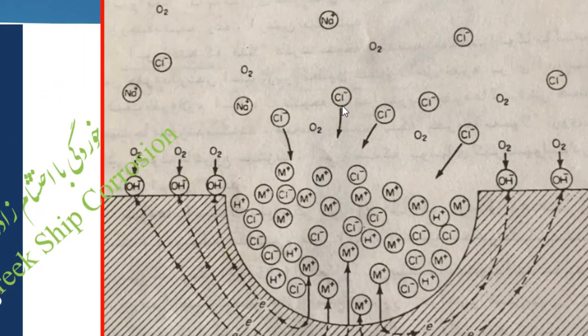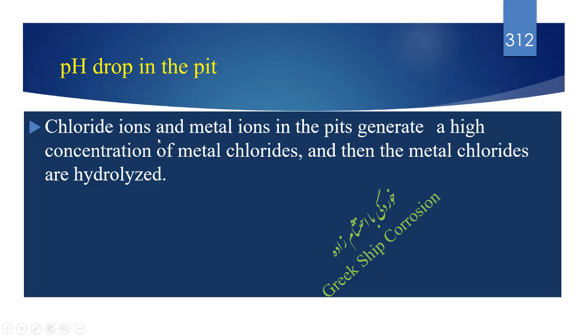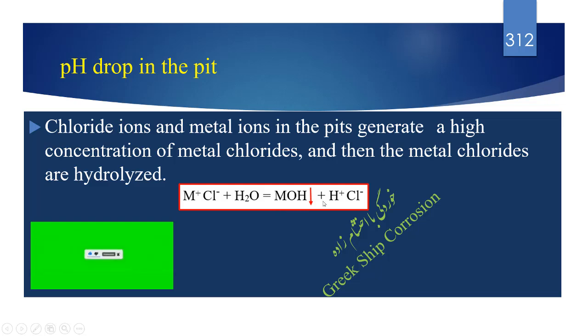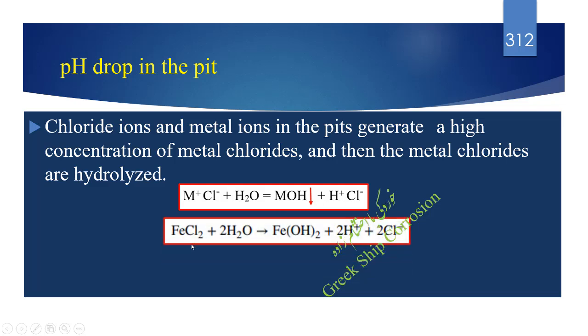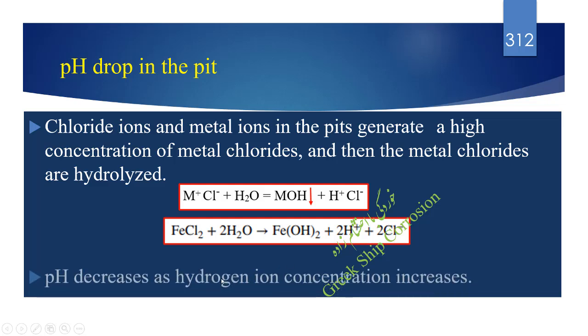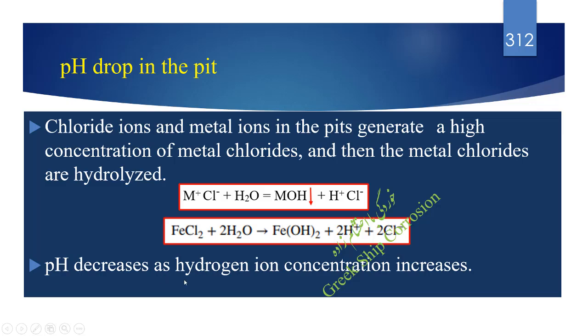Cl-, Cl-, Cl-. pH drop in the pit. Chloride ions and metal ions in the pits generate a high concentration of metal chlorides, and then the metal chlorides are hydrolyzed. MCl + H2O equals MOH + HCl. FeCl2 + 2H2O yields Fe(OH)2 + 2H+ + 2Cl-. pH decreases as hydrogen ion concentration increases.